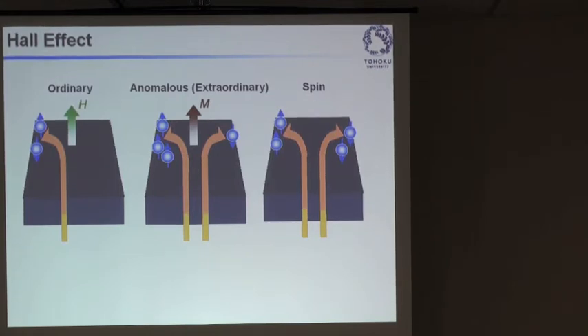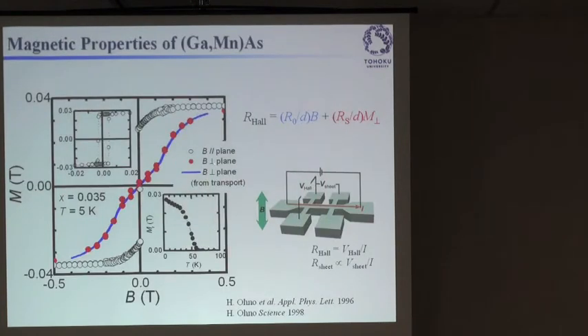We also know that David Awschalom is attending this conference. He has imaged this effect, the spin Hall effect, which was very difficult to measure because there was no voltage developed across. But the anomalous Hall effect is there with finite magnetization, with spin polarization, and you can detect the spin scattering by measuring voltage. So that's the reason why we have been able to closely monitor magnetization by Hall voltage.